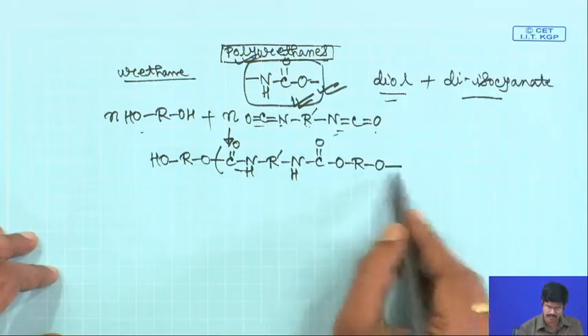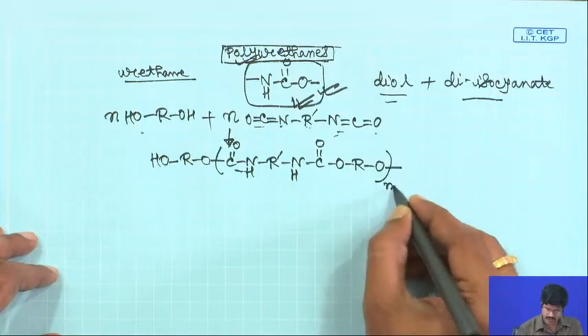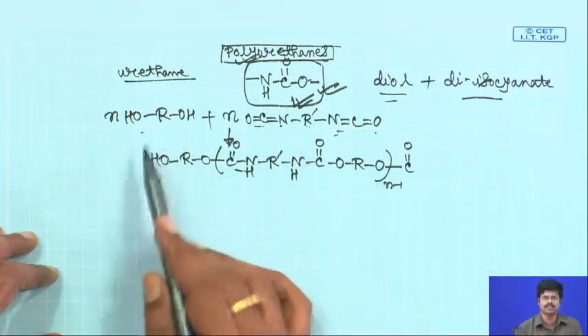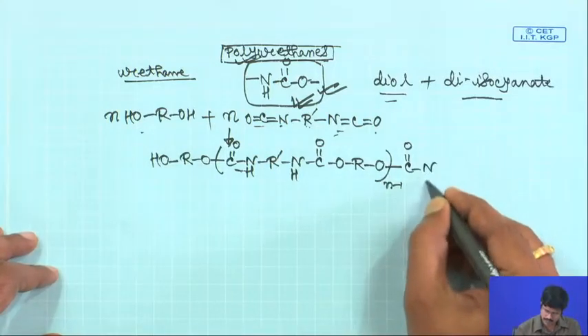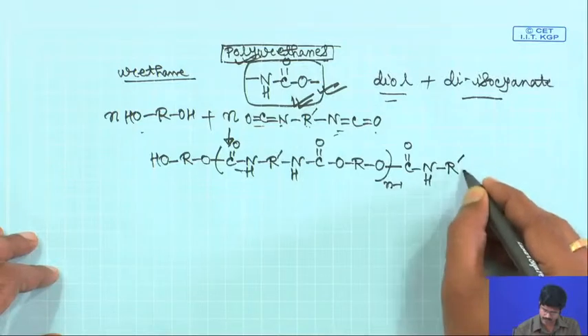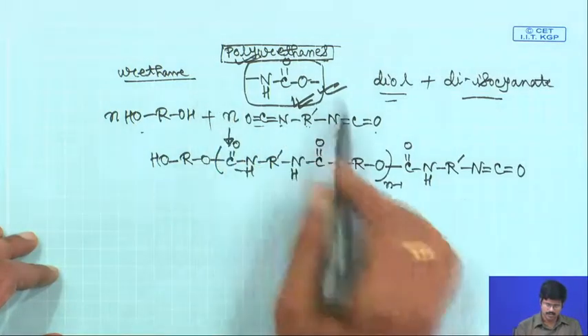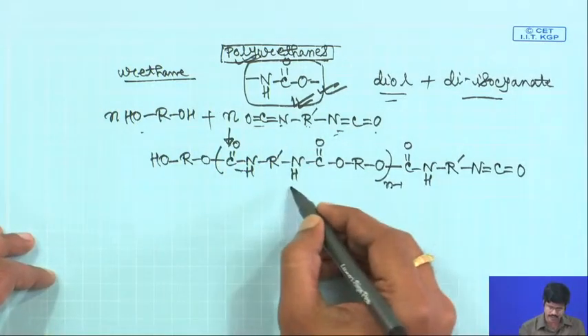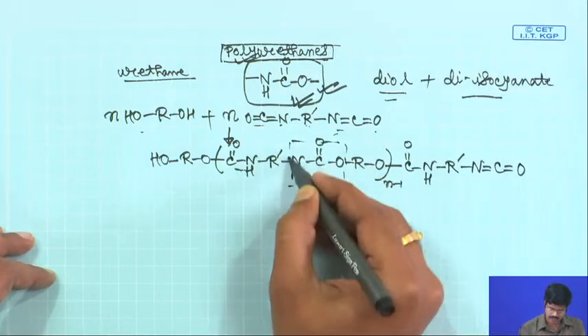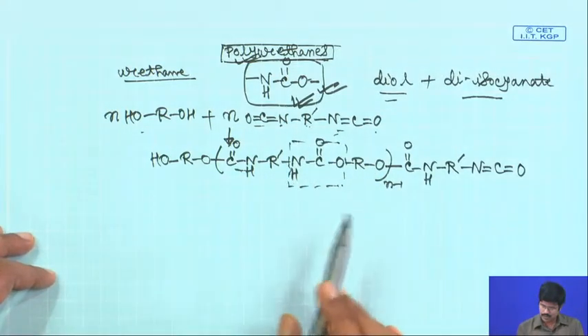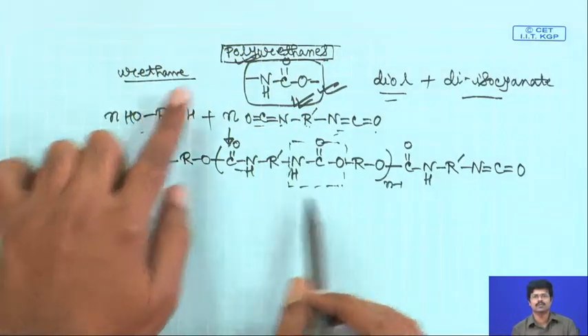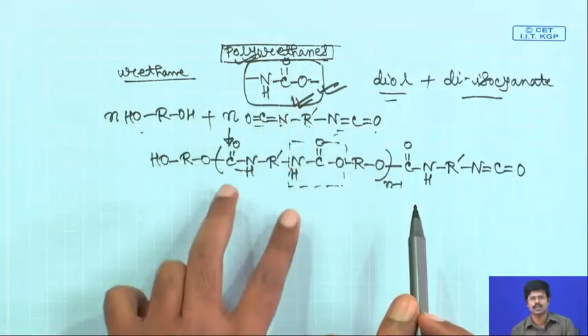This is an urethane linkage, and the alcohol also has to be in the repeat unit. With stoichiometric amounts, one end will terminate with isocyanate and the other with alcohol — giving you N-H-R'-NCO. This is your polyurethane with the urethane linkage. This is a simplistic way of depicting polyurethane synthesis: you take your diol and react with a diisocyanate and get your product.